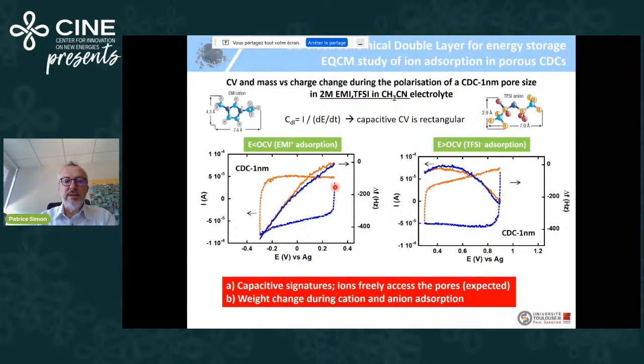What you see is that we have more or less a rectangular shape cyclic voltammetry. This is typical of capacitive storage. It means that a rectangular cyclic voltammetry is typical of ion adsorption-desorption with no redox reaction. Why? Because Q is C multiplied by V. So C is I divided by dE over dt, and dE over dt is the potential scan rate. So when the potential scan rate is constant like here, if you assume that your double layer capacitance is constant, then you have a constant current.